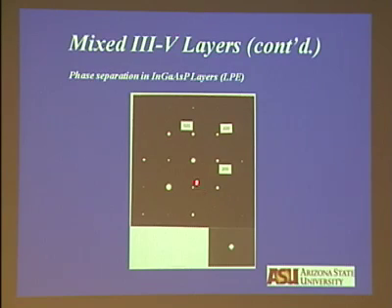This is the electron diffraction pattern from the 001 position, and what you see is when you enlarge these two 000 spots, it is not circular. It has satellites, intensity around the Bragg position. And from the position of the satellite with respect to the Bragg spot, you can determine the wavelength. Lipson did it in 49 in a Proceedings of the Royal Society paper, so you can apply the idea.